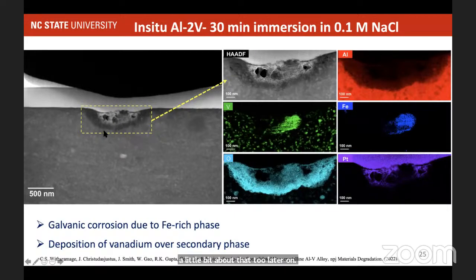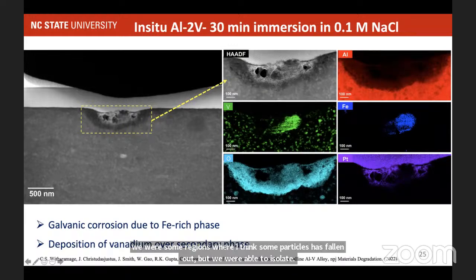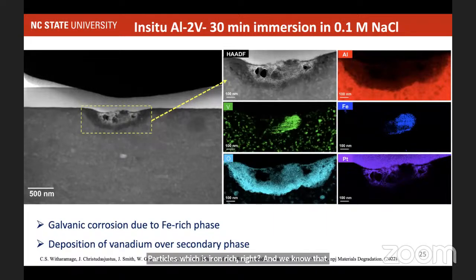We looked at where the corrosion initiated. So this is one example. Again, you see there's a 500 nanometer scale, and this region over here is a corrosion pit, right? So we start having the background of the passive film, and we start forming those pits, right? And now, if I look very closely inside the passive film, we have some regions where I think some particles have fallen out, but we were able to isolate a particle which is iron rich, right? And we know that these iron rich particles cause the corrosion in these aluminum vanadium alloys. This iron is coming as an impurity. The milling media we were using was stainless steel, so some of that iron is coming from there, right?